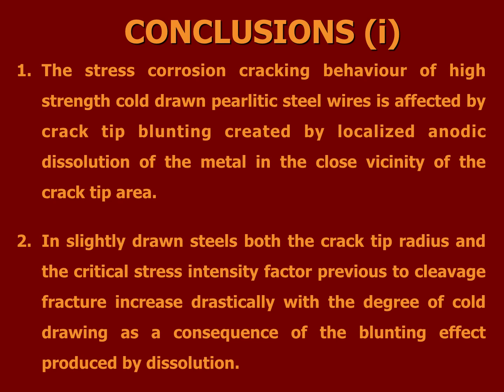Finally, the conclusions. 1. The stress corrosion cracking behavior of high-strength cold drawn pearlitic steel wires is affected by crack tip blunting created by localized anodic dissolution of the metal in the close vicinity of the crack tip area. In slightly drawn steels, both the crack tip radius and the critical stress intensity factor previous to cleavage fracture increase drastically with the degree of cold drawing, as a consequence of the blunting effect produced by dissolution.